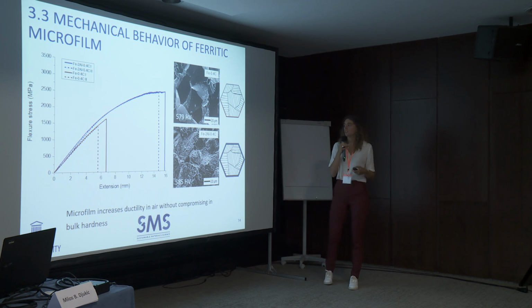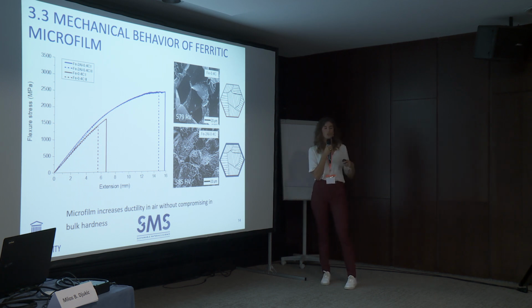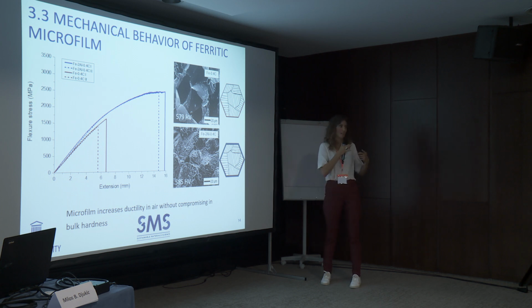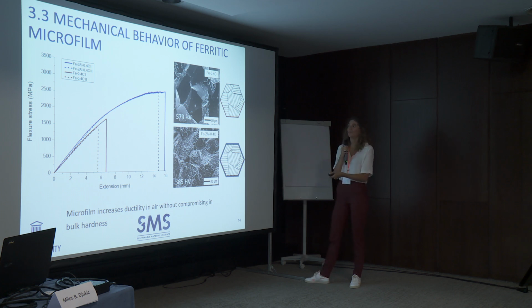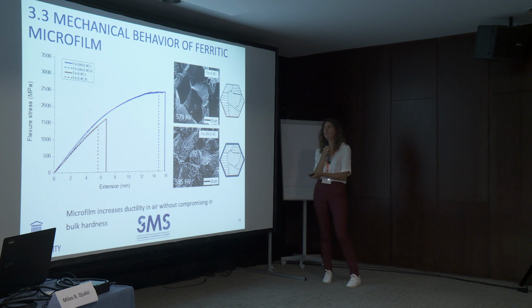The yield strength of ferrite is much lower than martensite, so it really is the carrier of the plastic deformation. So in fact, it acts as a kind of glue and holds your martensitic structure together. You can also see that the hardness values are very similar. So we introduced ferrite, but we didn't influence the hardness, which is very good.